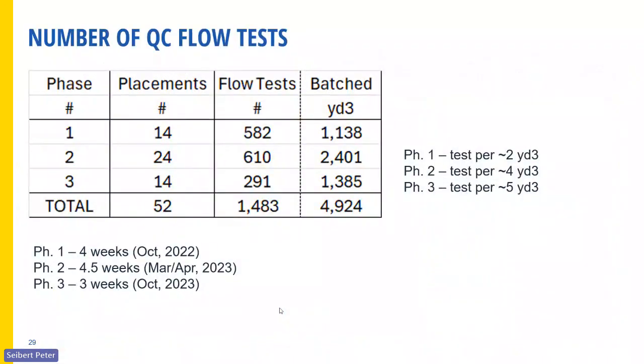Now this is quite something too. Because we had initially smaller batch sizes, we started with 2 yards per batch, then 4, and then 5. Overall for this project, we did 4,924 cubic yards, which is a lot of UHPC. This is generally how much maybe the entire North American UHPC industry uses in 1 year for joint fills, precast, girders, all that's out there, and this one project used that much. We also did almost 1,500 flow tests. So it kept Jack pretty busy.